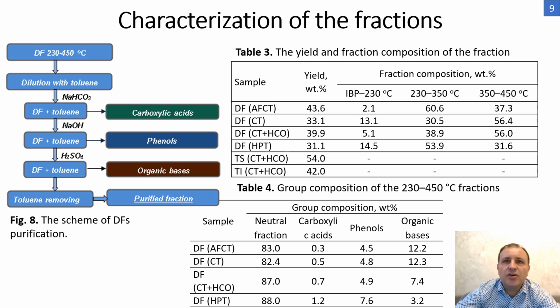The ninth slide shows a scheme of distillate fraction purification in figure 8 and the obtained results. The group composition of distillate fractions depends on the type of solvent used for coal dissolution. Distillate fractions from coal extracts in heavy pyrolytic tar contain more oxygen-containing compounds, namely phenols and carboxylic acids.